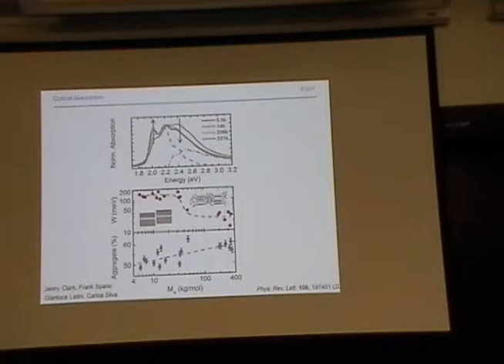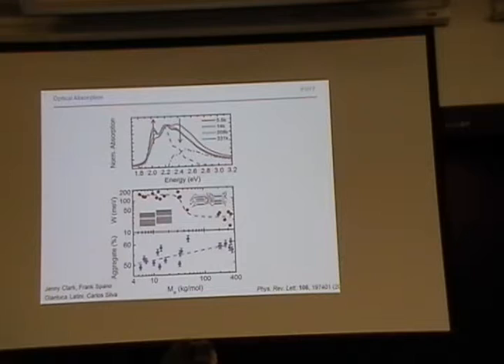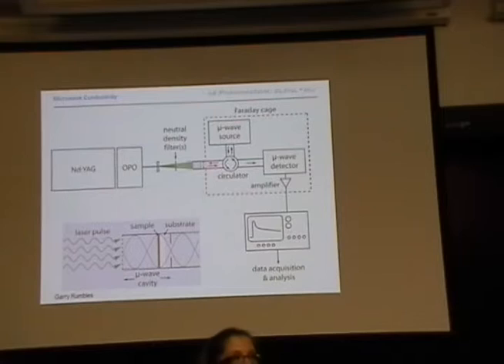We also get information on aggregates. It tells us we have more photo-physical aggregates in the system. What this also tells us is that photo-physical aggregates — they are actively leading to a higher zero-zero absorption — not necessarily meaning more crystals. So it simply means you possibly have two chains that are stretched out coming together. However, the free exciton bandwidth I think is very telling, and in particular how drastic this change is from chain-extended crystals to the semicrystalline morphology.